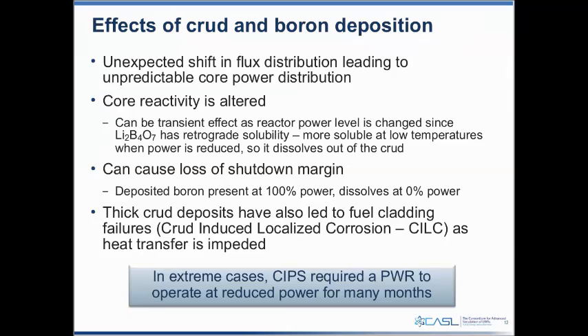Interestingly, these lithium-boron compounds have retrograde solubility. Typically things are more soluble at high temperature compared to low temperature, but lithium tetraborate goes the other way - it's actually more soluble at low temperature. So when we're operating the core at full power, we're depositing the lithium-boron compound. But if we reduce power, meaning we're also reducing coolant temperature, the lithium-boron compound can dissolve back out of the crud, so now core reactivity is changing as we change power level.